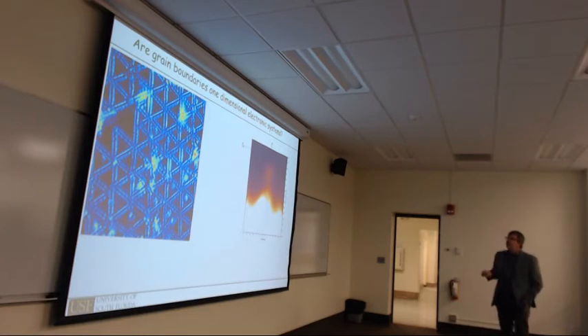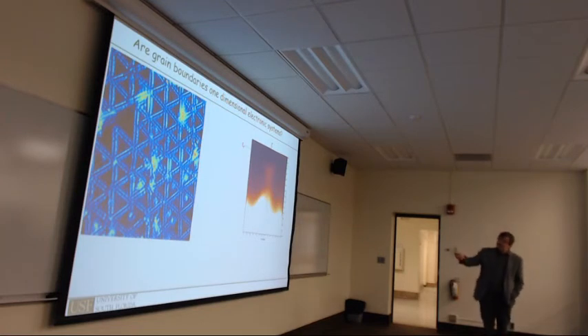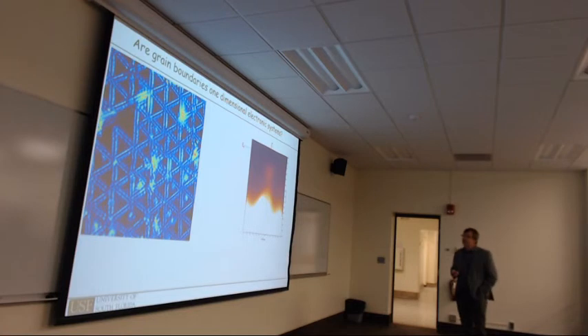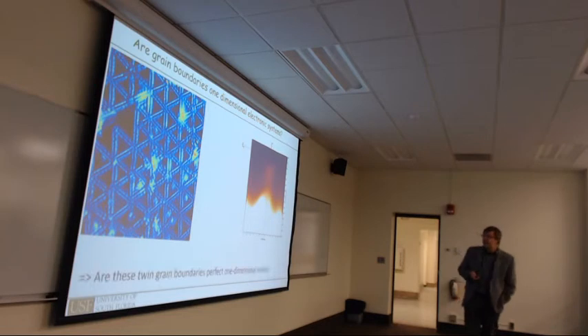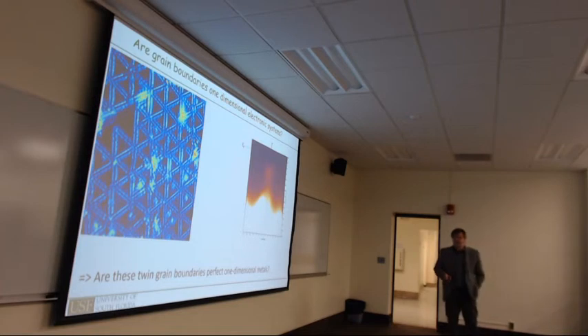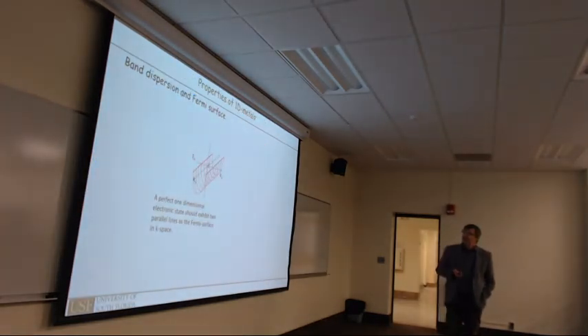Which is shown here. So as I said, molybdenum diselenide is a semiconductor, so this is the Fermi level. These are the bands of molybdenum diselenide. So you have a band gap. And if you look carefully in the band gap, you get this state, which is a kind of parabolic dispersive defect state or band gap state, which arises from these twin grain boundaries. And it seems like they intersect the Fermi level, so that would suggest this is a one-dimensional metal embedded in a semiconducting matrix. We can look a little bit more carefully at the band dispersion.